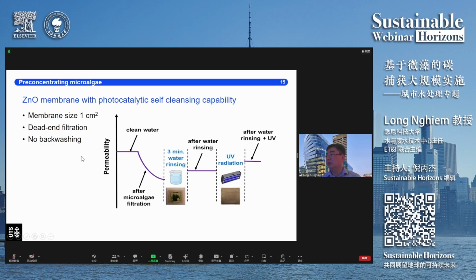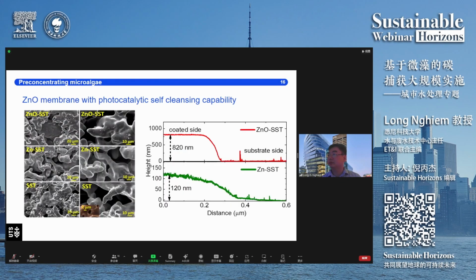So we use the membrane to filter microalgae solution. In this case, we use the species that causes the most problem, which is Selenastrum. And then we rinse it, and then we irradiate with UV to check the flux recovery. But let me show you our data regarding the characterization of the zinc oxide coated membrane.